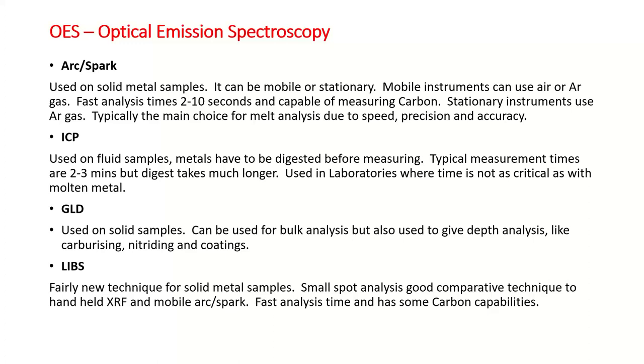It's normally very fast, somewhere between 2 and 10 seconds. One of the main things that arc spark can do is measure carbon. So people are looking for carbon in a steel sample, and it's a very good technique to be able to do that. Stationary instruments, as we say, a lot of melting shops, casting companies, stockists, these sort of people, they will have a stationary analyzer, and it will be an arc spark one typically, and basically presenting your sample and getting a result from there.